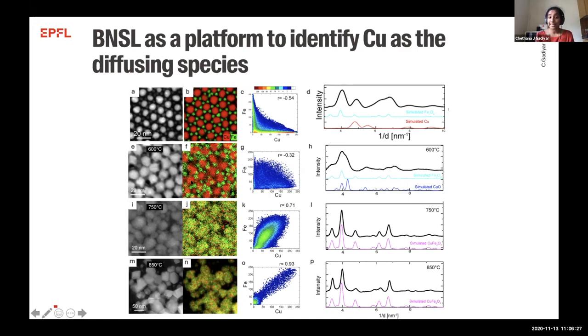Already from the sample at 600 degrees Celsius, we were able to confirm that copper is indeed the diffusing species. And if we want to have control over the shape and size of these nanocrystals, it's important to control the diffusion of this copper species.